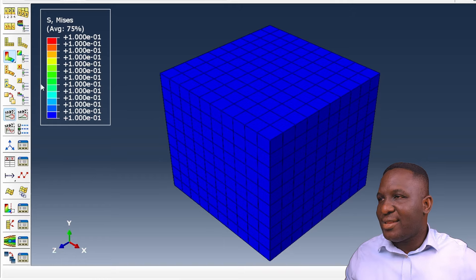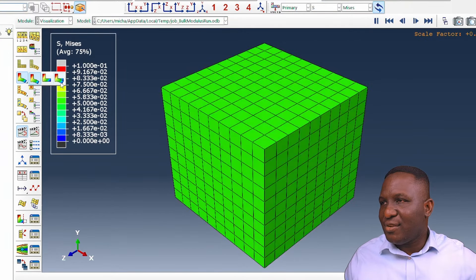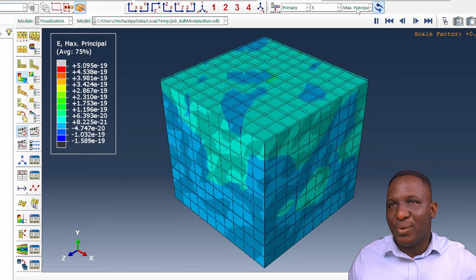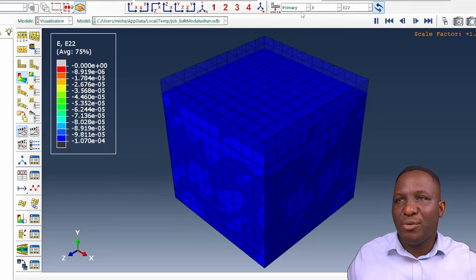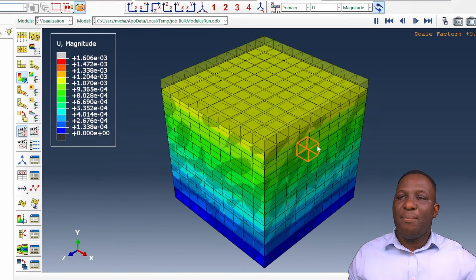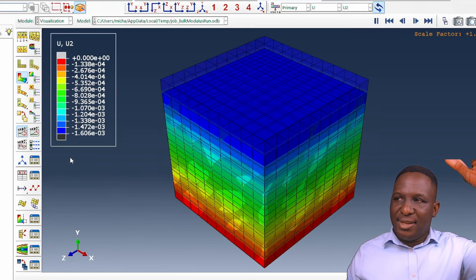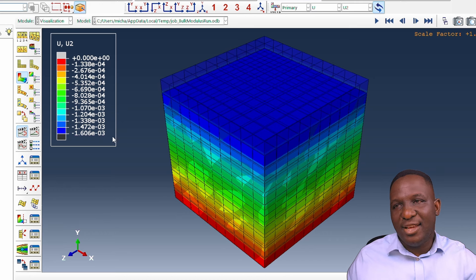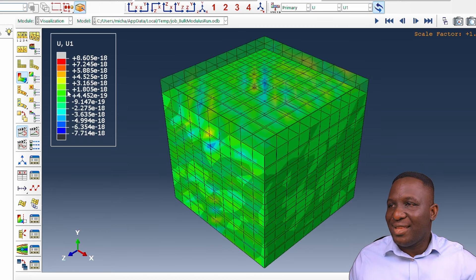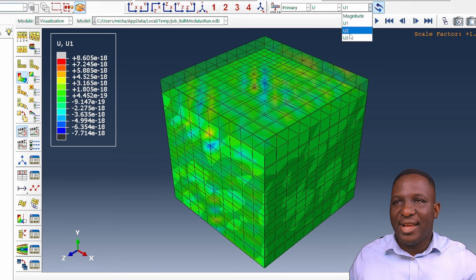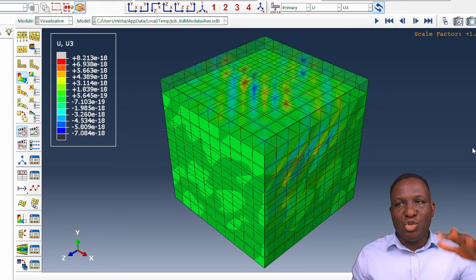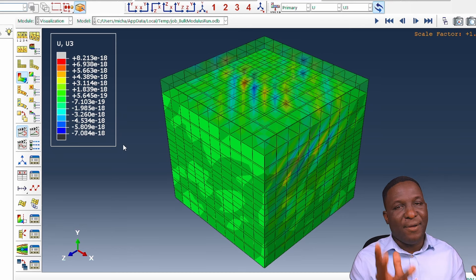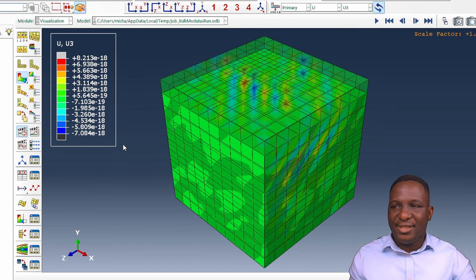The simulation is finished. Looking at the animated result, you can see what's happening — before and after images show a nice compressive behavior with no lateral movement. Looking at the strain in the 2-direction, we have a nice model setup. In terms of displacement, the system moves down perfectly correctly. From top to bottom, the base is zero and the top experiences maximum displacement of 1.606×10⁻³. In the 1-direction everything is zero — no contraction — and in the 3-axis there's also no change. Compression is occurring only in the 2-axis as intended, confirming a perfect experimental setup for calculating bulk modulus.